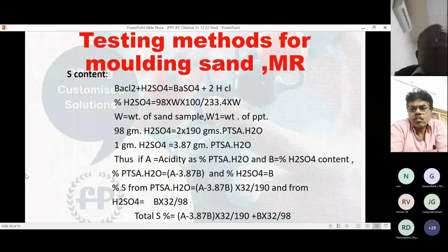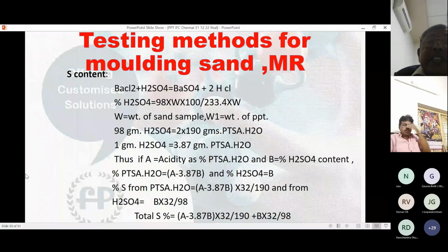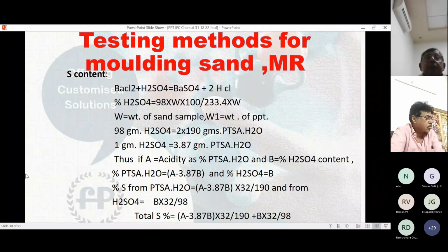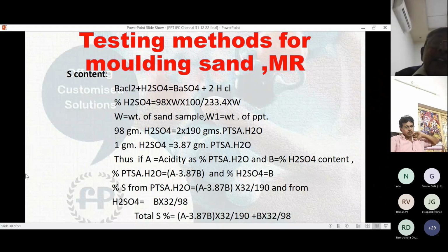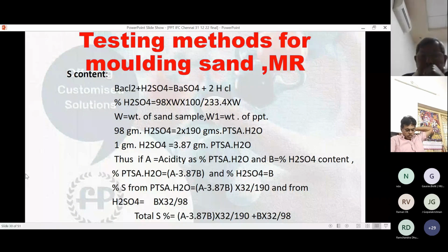Barium chloride forms a sulfate precipitate with sulfuric acid only, but not paratoluene sulfonic acid. The barium sulfate formed is a very silky precipitate. You just filter it with a Gooch crucible number 4 with the help of a vacuum pump. The Gooch crucible will retain all the sulfate as barium sulfate, and by weighing that gravimetrically, you know how much barium sulfate has come, and that is equivalent to how much sulfuric acid, and that sulfuric acid is equivalent to how much paratoluene sulfonic acid. So deduct the sulfuric acid equivalent from the total as paratoluene sulfonic acid. Now you get 2 components with sulfur bearing. One is PTSA, another is sulfuric acid.